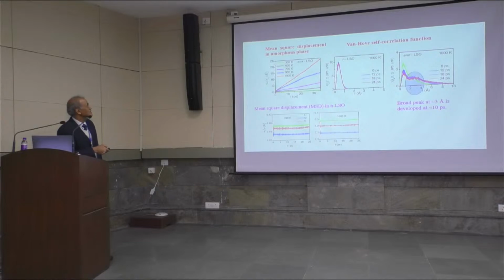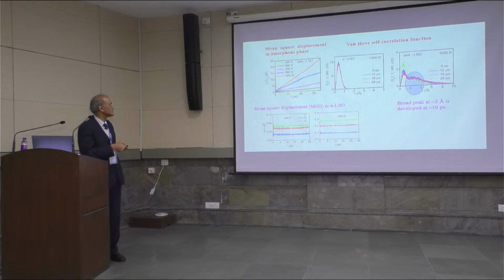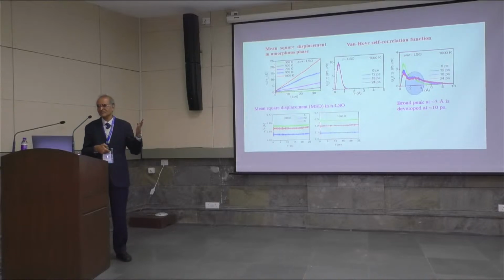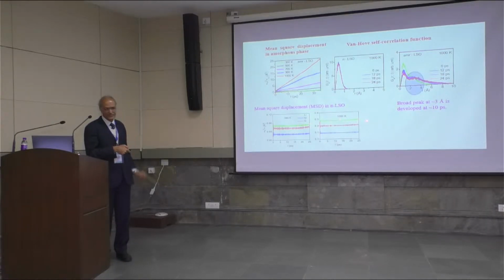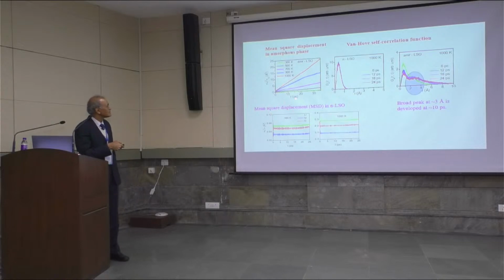Okay. Now you can also, for example, do a simple molecular dynamics calculation. You can calculate the mean square displacements of atoms. In a crystalline material, the mean square displacement does not change with time. These are just the phonon vibrations. So the mean square displacement is practically independent of time, and it increases with the temperature. But this does not indicate diffusion. However, if the mean square displacement increases with time in a molecular dynamic simulation, then that indicates diffusion.